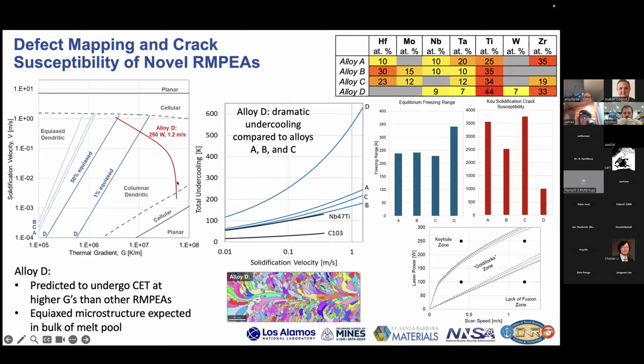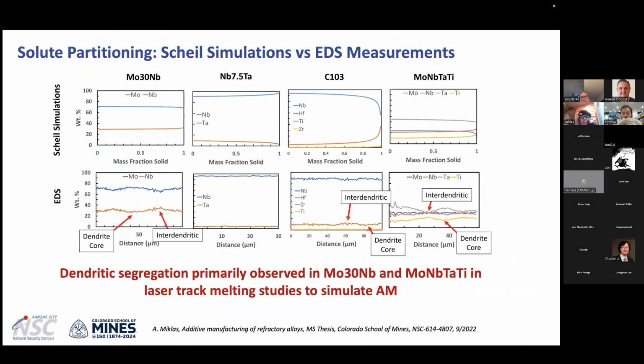And then if we kind of compare the mapping that she's done and the GV traces that are going to be experienced in a melt pool track that we've laid down, she would expect to see some refined grains in the melt track. And indeed, she does see refined grains in the melt track. So this is an area that we're moving forward. These kinds of assessments are obviously much more complicated for multi-component alloys, and this is something we're trying to better understand. And I'll say Teresa has some students working in this space as well.